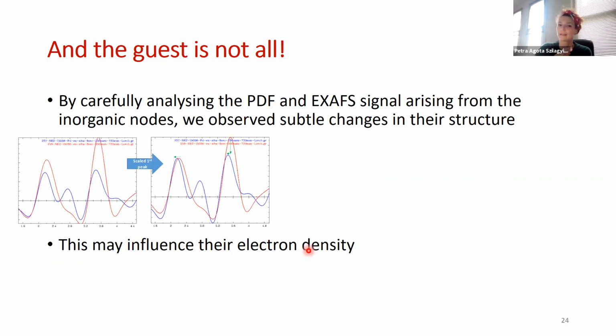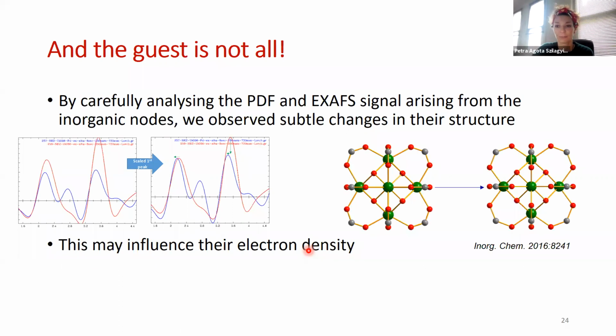Remember, these are hexanuclear, so they only contain 14 atoms in total, including zirconium and oxygen. This is a similar idea we'd find in the literature. The changes are maybe not that stunning, but you can see perhaps the zirconium-oxygen-carbon angle is different, and perhaps more significantly, the zirconium-oxygen bond length changes as well. And this is obviously very important for acidity.